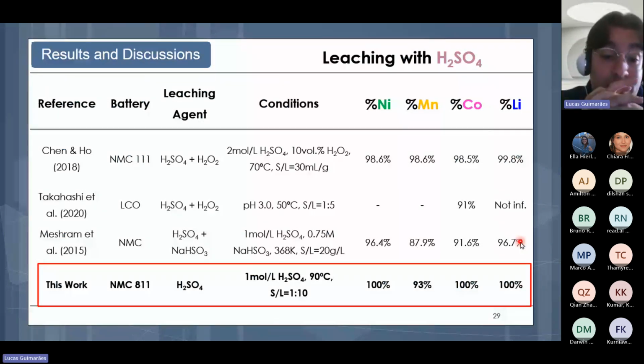So the results, in the best condition for leaching with sulfuric acid, showed that it was able to recover 100% of nickel, cobalt, and lithium, and 93% of manganese were leached, doing the leaching with these acids.